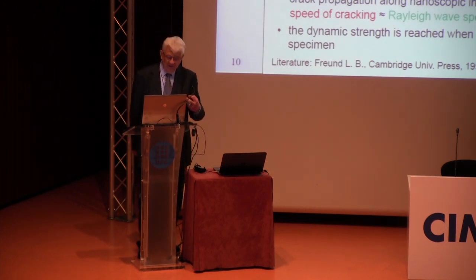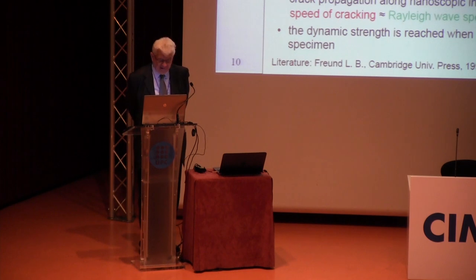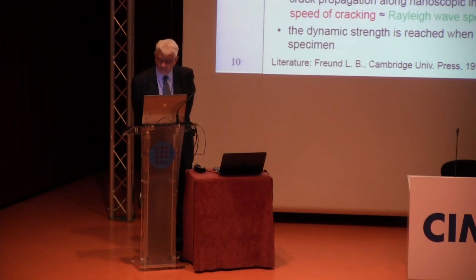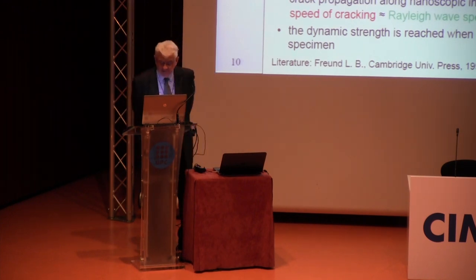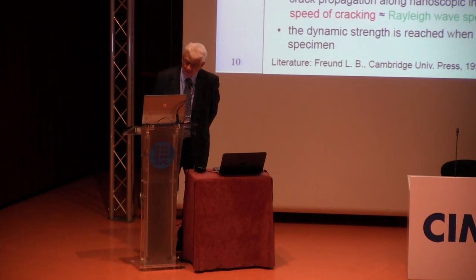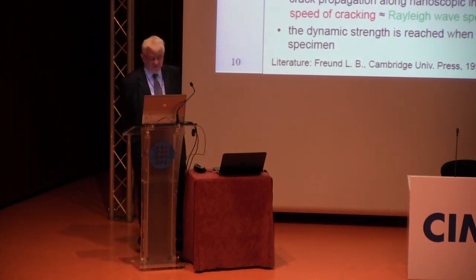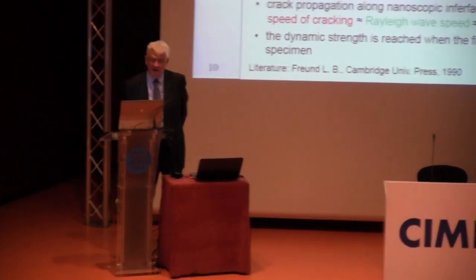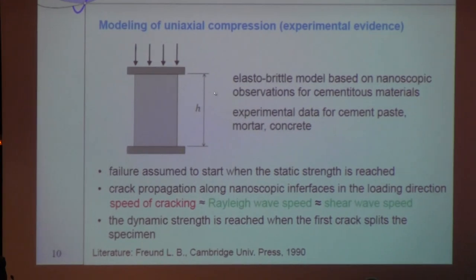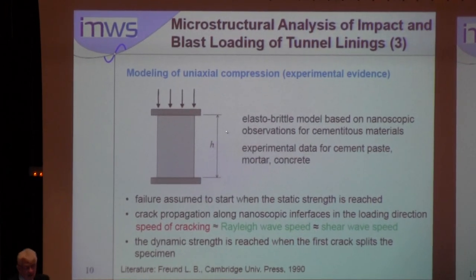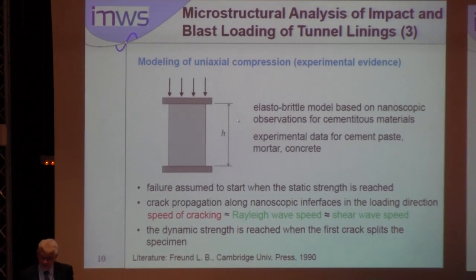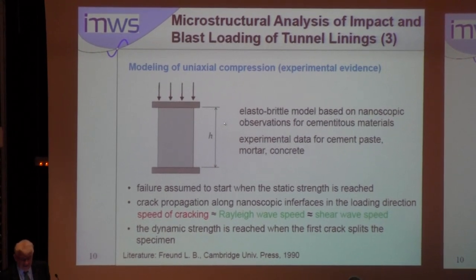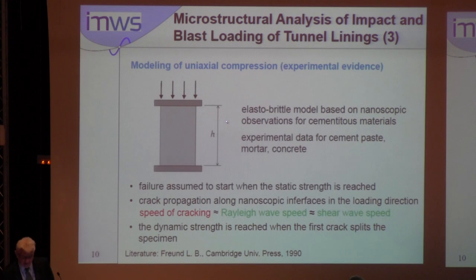There is particularly much experimental evidence for uniaxial compression. This was the basis for our elastobrittle model based on nanoscopic observations for cementitious materials, using experimental data for the cement paste, mortar, and concrete. Failure was assumed to start when the static strength is reached. Crack propagation is assumed to occur along nanoscopic interfaces in the loading direction. The speed of cracking is approximately equal to the Rayleigh wave speed, which is approximately equal to the shear wave speed. The dynamic strength is reached when the first crack splits the specimen.